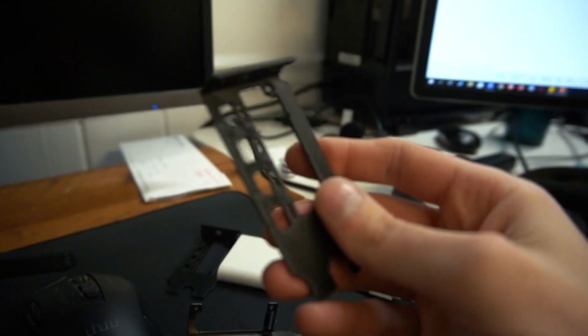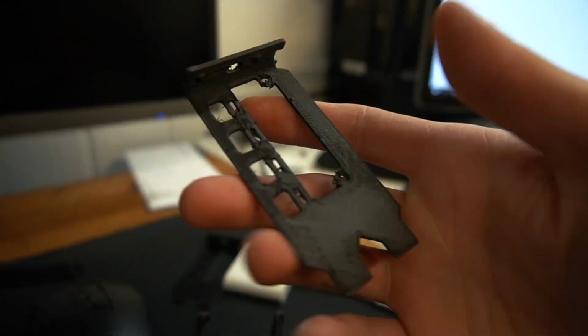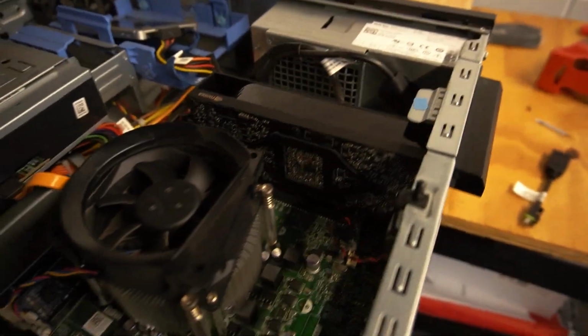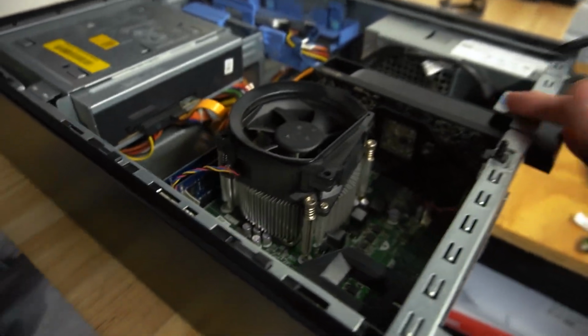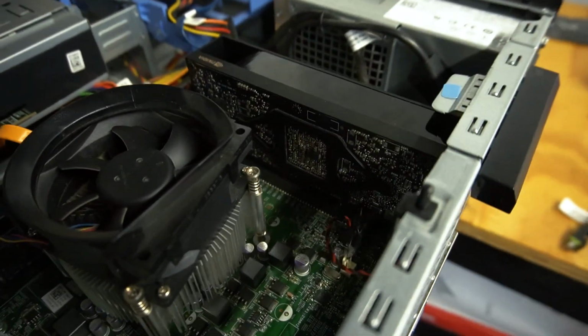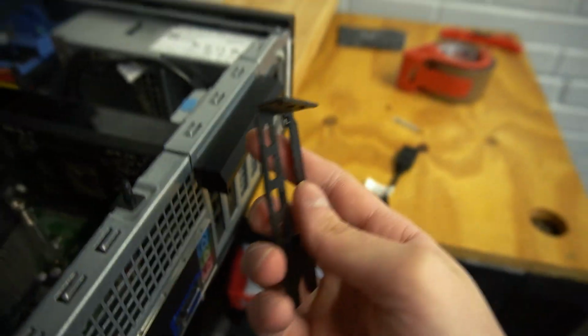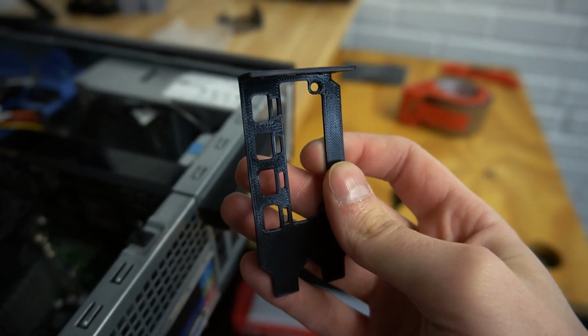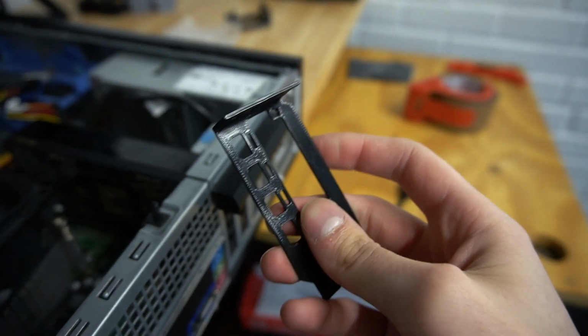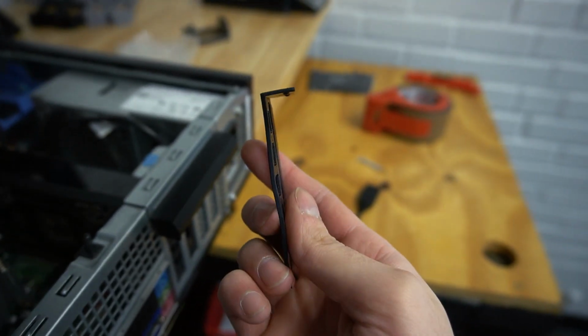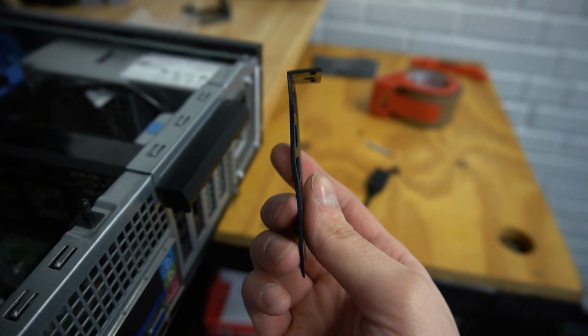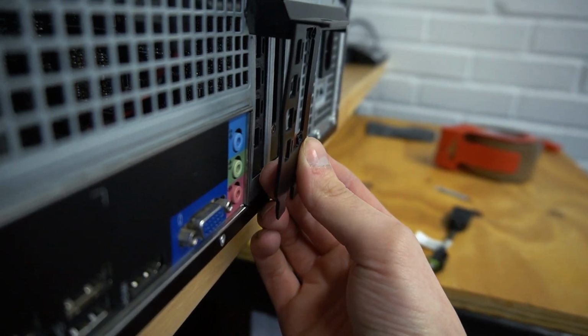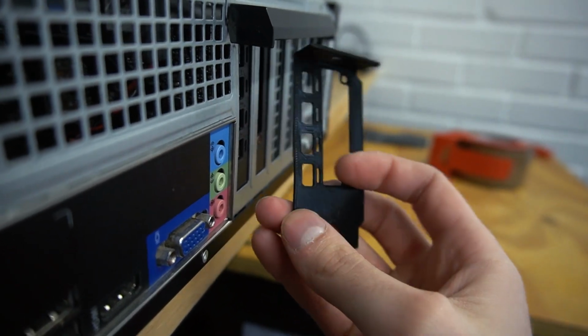I think it's this one. It didn't turn out any better. And then I went to carbon fiber nylon to see if it had more strength, and it just didn't print very well. So with that, I put it in a computer. This is a small form factor Dell Optiplex. I have OS on it and was mining on this A2000. And here I was doing a heat test, and it was fine at like 55C, 60C, but once it got past 65, you can actually see that it deformed just a little bit right here on the one side.